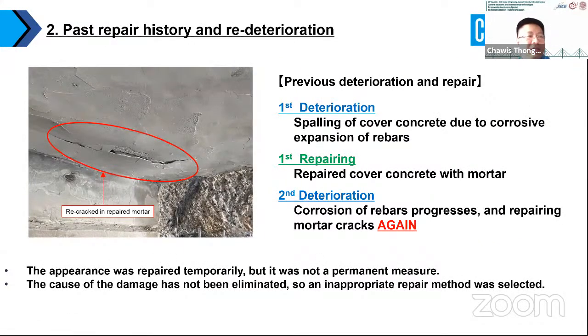Another problem, as we always see, is that some repair works on pier structures have already been done several times by the contractor. Repairing mortar was selected and applied on the concrete surface in this case. However, the chloride ions remain inside the concrete, and rainfall still continuously gets inside. The steel will expand because of the increase of surrounding oxide. Then the repairing mortar will crack again, as shown in the photo. The root cause of deterioration has not been eliminated, so this practice in the long run cannot extend the lifetime of the structure.